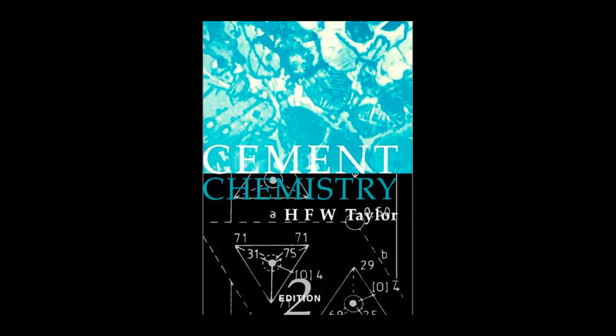Non-evaporable water is a crucial empirical measure. It represents the mass of water that's still held by the cement paste after a very stringent drying process, like D-drying, which is equilibration at -79 degrees Celsius under a high vacuum. It's an indicator of the amount of hydrate that's been formed. But you said it's an empirical measure, not a precise chemical measure. That seems like an important distinction.